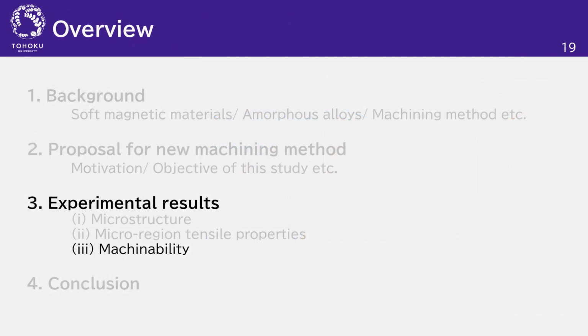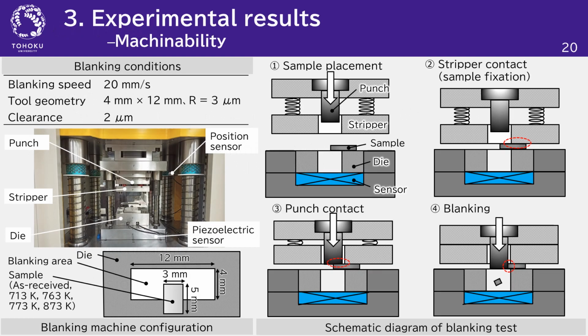Finally, the influence of the mechanical properties of the microregion on machining was investigated. In this experiment, machining tests were performed on the samples whose microstructure and mechanical properties had just been evaluated. We measured the machining resistance and evaluated the machining quality.